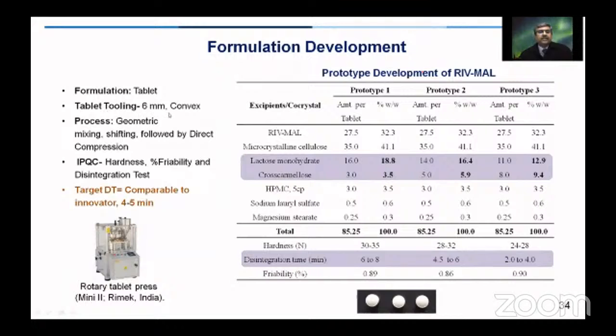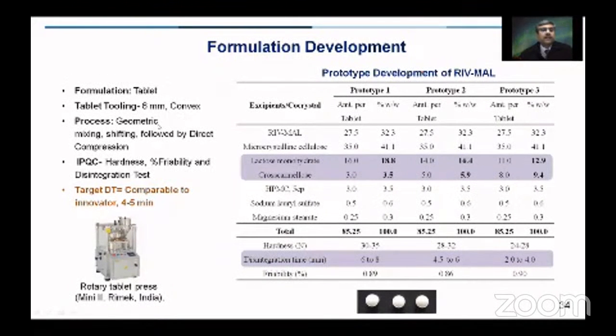The tooling was 6 millimeter convex tablet tooling. Process was a direct compression process. These were the in-process quality control parameters. The target DT was comparable to the innovator, that is 4 to 5 minutes, and the compression was carried out using a rotary tablet press.